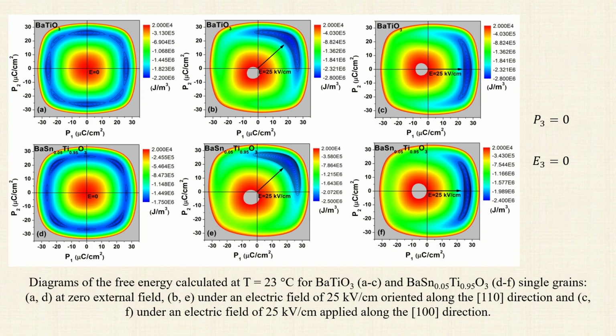In these images, the diagrams of the free energies are presented as dependent on two components of the polarization, P1 and P2, while the third one is considered equal to 0 for the simplicity of the representation. In the absence of an external electric field, we can observe that both systems present stable orthorhombic and tetragonal phases, but with lower energy values in the tetragonal phase for pure barium titanate and lower energy values in the orthorhombic phase for solid solutions. When dealing with Landau theory, many authors interpreted the first diagram as corresponding to a tetragonal phase, because the minimum of energy is established in this state.